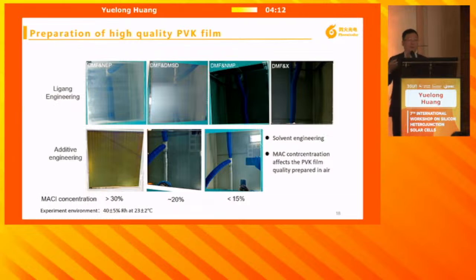To make a good film is not that easy. For publications, you always make it by spin coating. But when you are making slot die, larger area, this is only 30 by 30. When you are making even 2 square meters by slot die, then you really need to understand what is happening in the environment. If you use a different additive or a different solvent, the result is completely different.